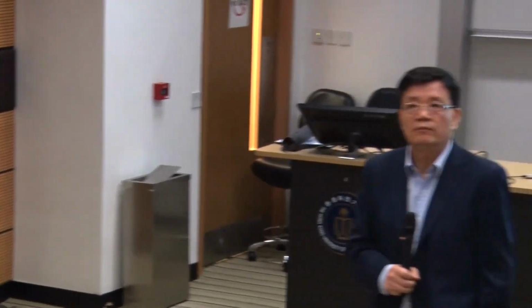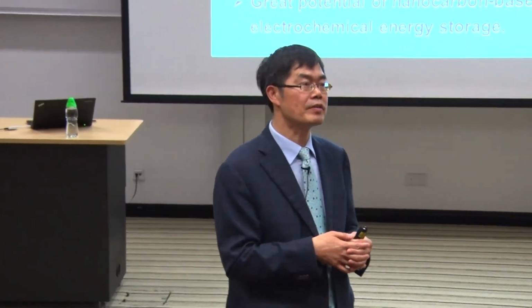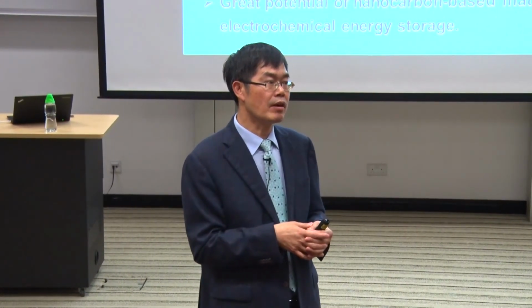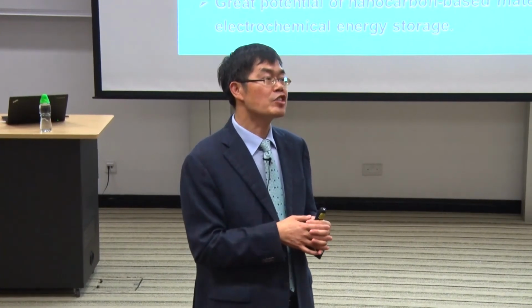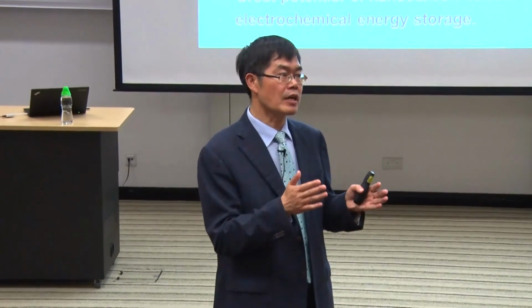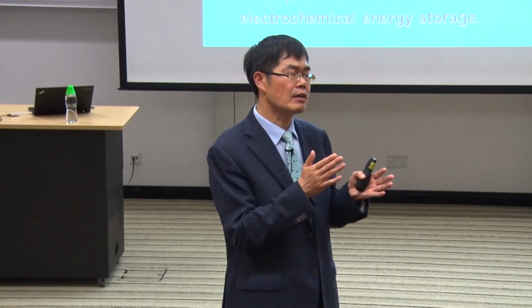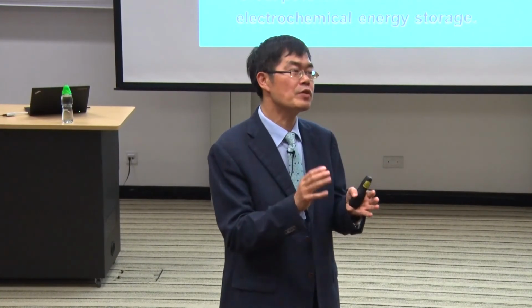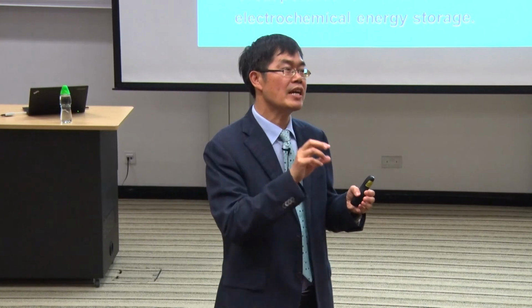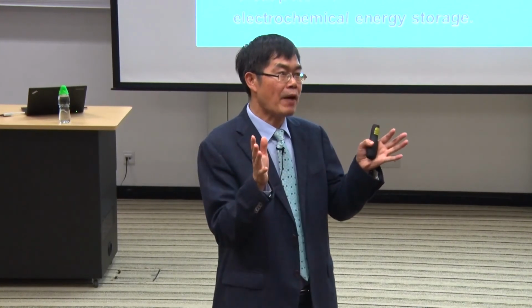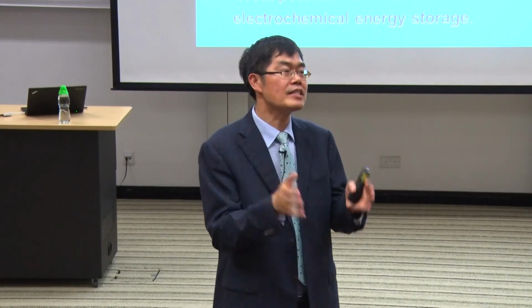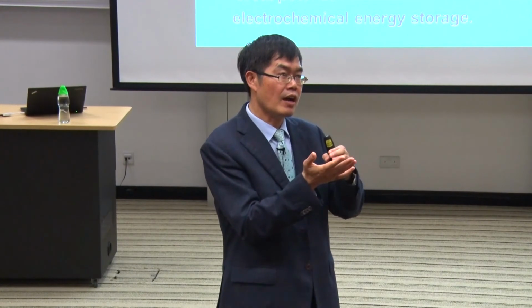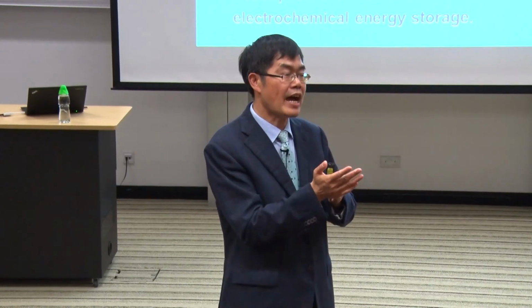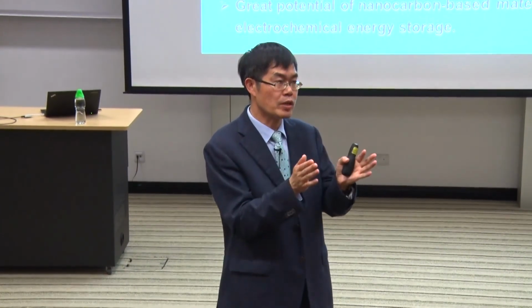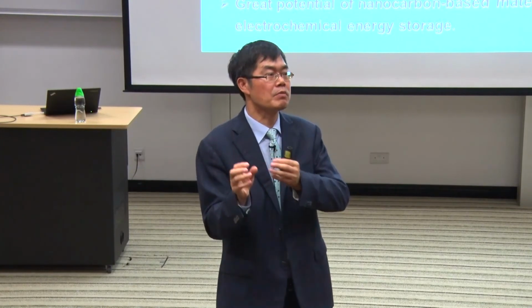So the first question is about the interaction between metal oxide and carbon material. Yeah, as you said, it's very important. We can improve the interaction between metal oxide and carbon material by functionalization. For example, we found that if we use graphene oxide or lightly reduced graphene oxide, which means we still have quite rich oxygen-containing functional groups, by a hydrothermal synthesis approach, the metal oxide can form some chemical bond with the functional groups of graphene.